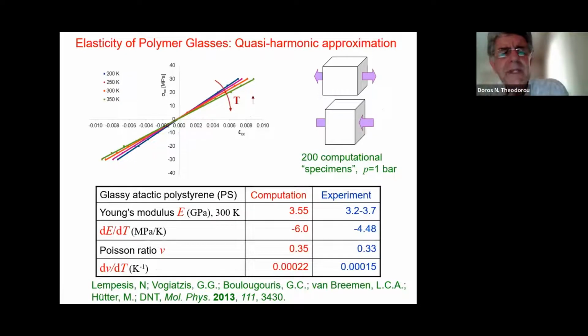Another thing that you can do for these glasses is you can perform mechanical deformation experiments on them. You can, for example, impose a stress tensor such that there is a tensile stress in the x direction, whereas the y and z directions are exposed to 1 atmosphere. Or you can even impose a compressive stress in the x direction. And you can again minimize the free energy and observe at what dimensions the system equilibrates when it is confined in its basin, and then average over many basins, in this particular case 200 basins, to get a stress-strain dependence. If the stress that you impose is relatively low, this stress-strain behavior is linear and reversible.